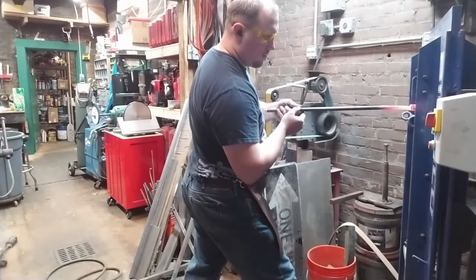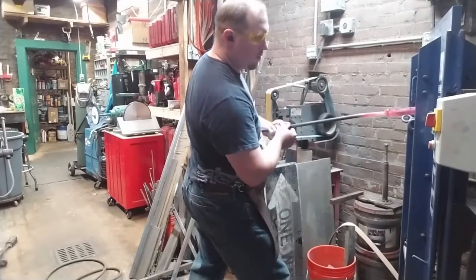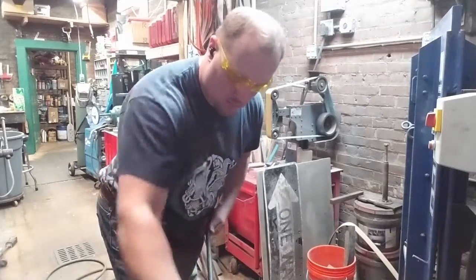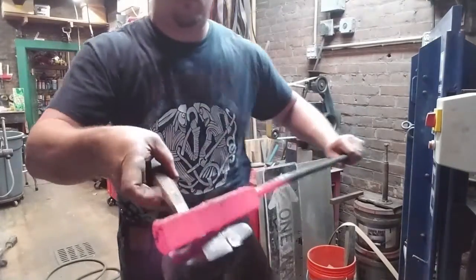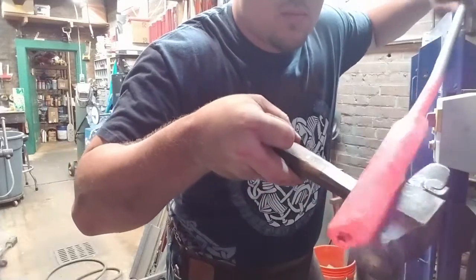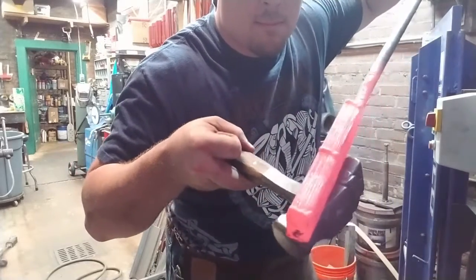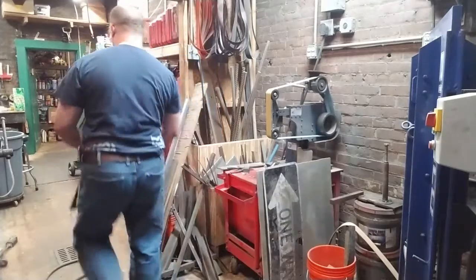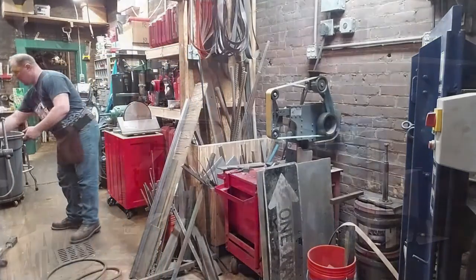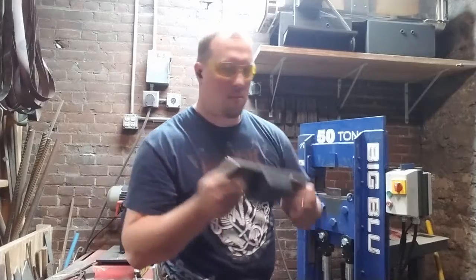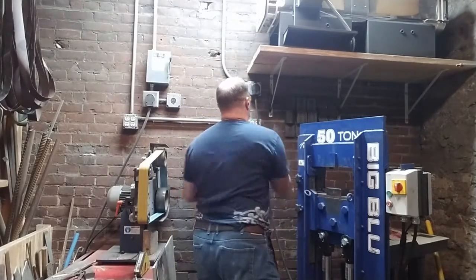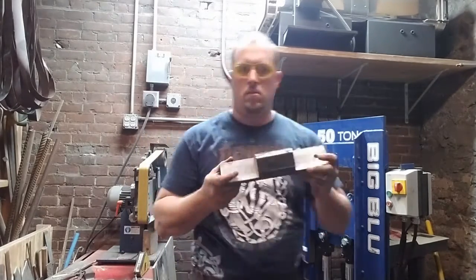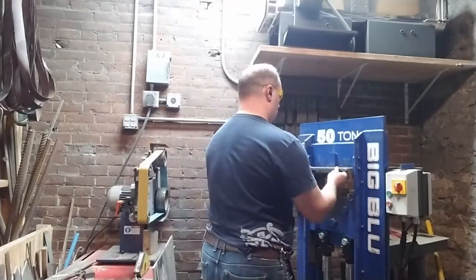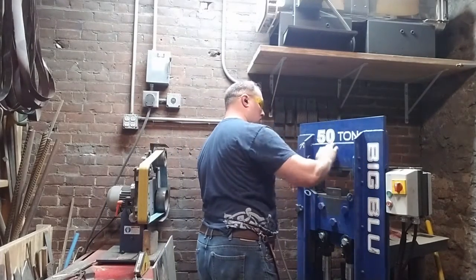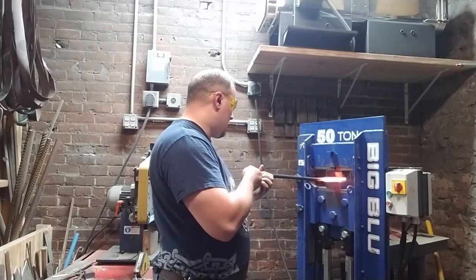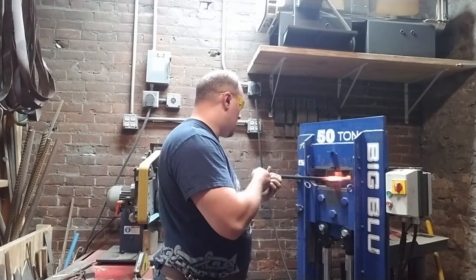I'm using the hydraulic press for the 3rd welding step. And in dealing with any kind of laminated material, you're going to want to work as hot as you can, especially if you have to work against the plane of the weld. We'll get to that a little bit later, because that's exactly what we will be doing. I'm switching the plates out from a flattening plate to a fullering plate, and that'll let the drawing process go a little bit more quickly. You'll see that here.